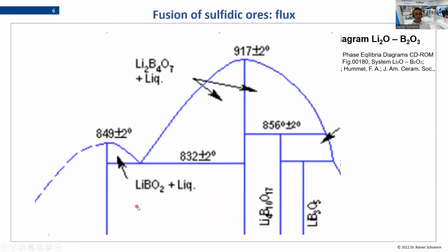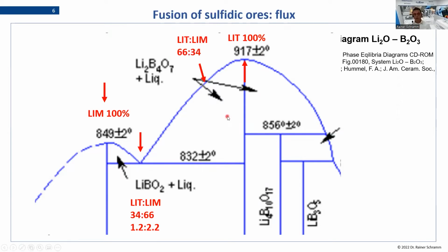And if I zoom in a little bit, you see here again the lithium metaborate with a melting point of 850 degrees and tetraborate with 917. Then we have here a eutectic mixture, which is 34% lithium tetraborate and 66% metaborate, or we call it sometimes 1.2 molar to 2.2 molar. And this is then the lowest melting point we can achieve in lithium borates, with 832 degrees. And the other mixtures, like the 66-34 tetraborate, metaborate, is around here, and 50-50 would be around here. So you see, this is our playground with the lithium borates we can use for fusion, for XRF.